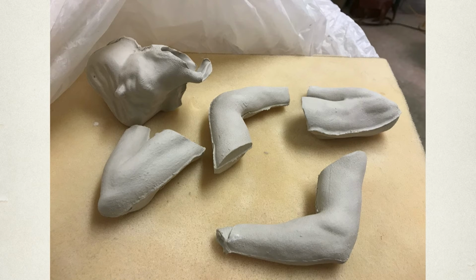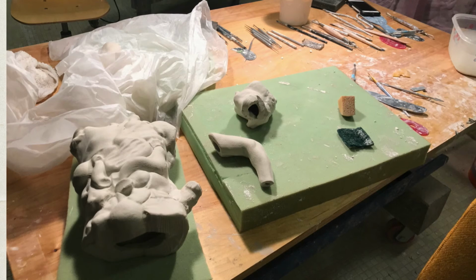Probably the easiest thing. Is that clay? Was that part cast? Oh yes, we're casting clay here. This is a porcelain casting slip. We ended up press molding. Really, the issue was that my mold was still too wet to do a good slip casting. But it's press molding, popping it out.